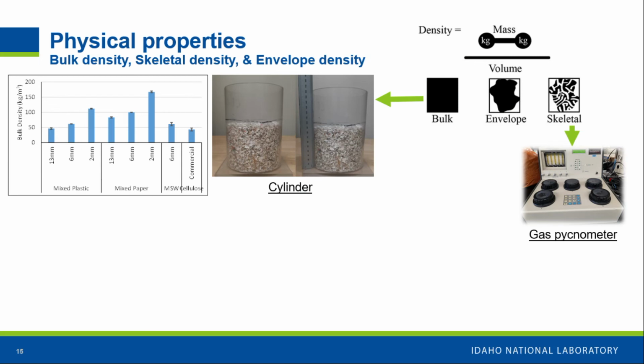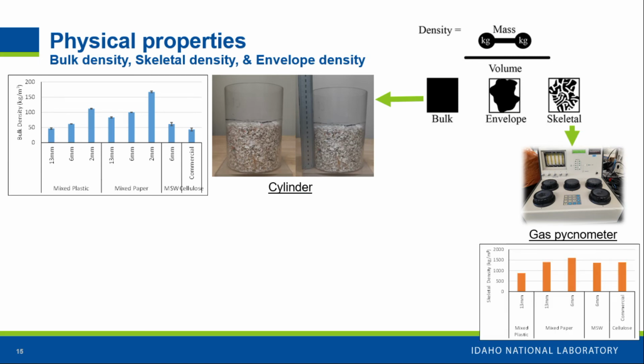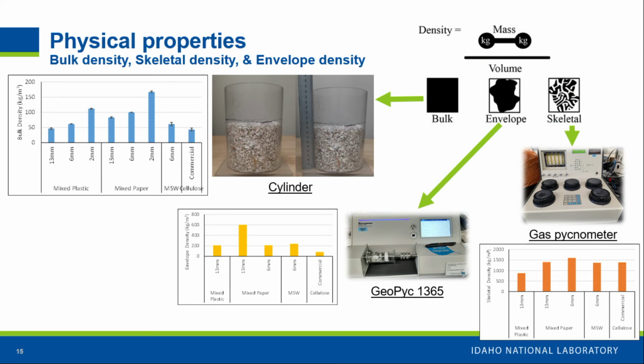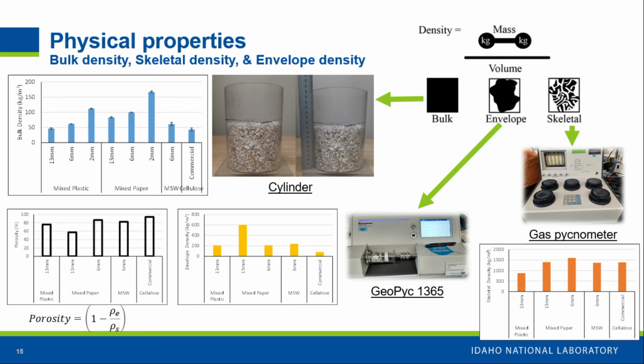We checked the skeletal density of the material, and we saw that skeletal density also changes with different materials as well as the size of each material. A similar thing happened to the envelope density as well. When we check the envelope density and skeletal density and see the porosity of the material, we saw that cellulose has about 95% porosity, where our MSW also has higher porosity, about 85-ish percent. That means we had some sort of feeling we might get similar insulating behavior from the municipal solid waste compared to the cellulose.